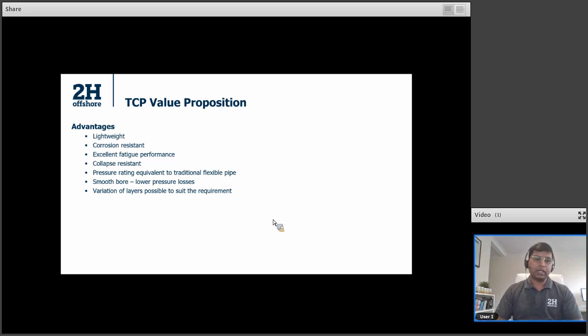And this again goes back to the technology itself, where you can have multiple strands, multiple layers of polymer composite layers, so that you can increase or decrease the thickness, you can increase or decrease the alignment of the fibers to get the required strength. TCP pipes are smooth bore, which means lower pressure losses across the length of the flow line, or riser, which means you can get the same level of delivery of the content with a smaller ID pipe. And variation of the layers is also possible to suit the requirement.